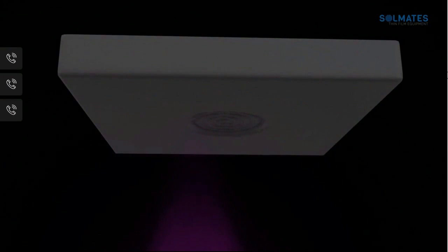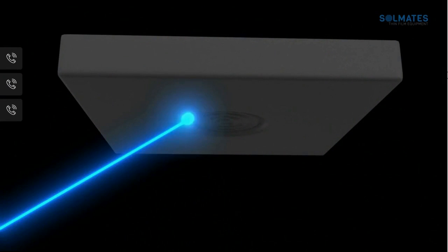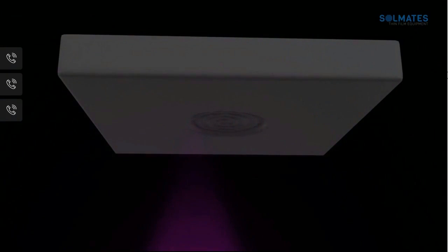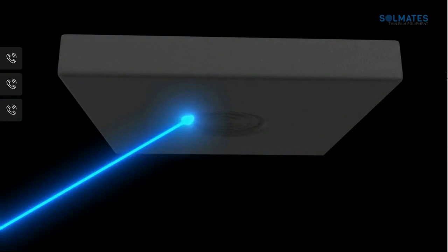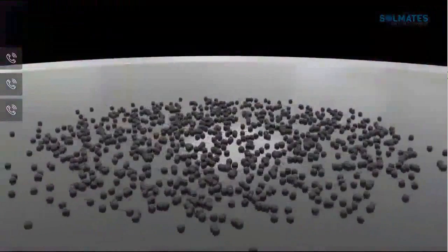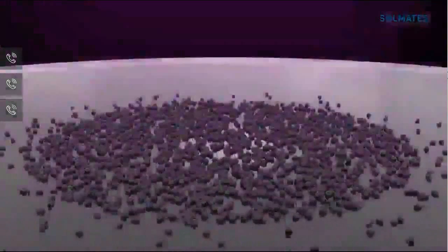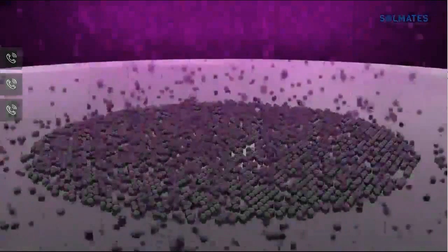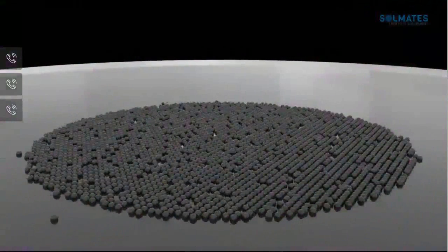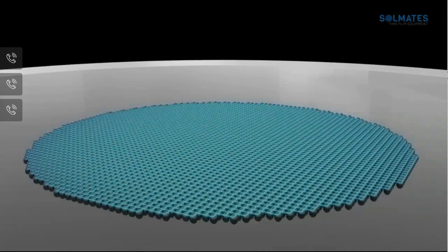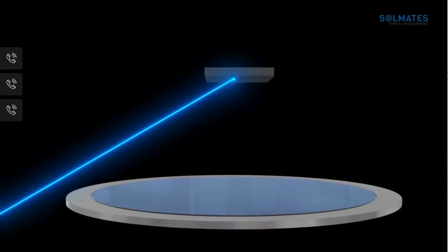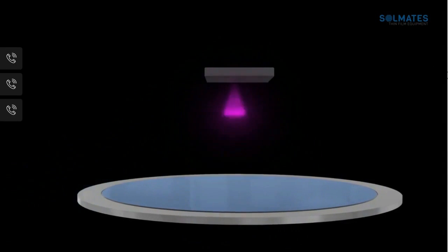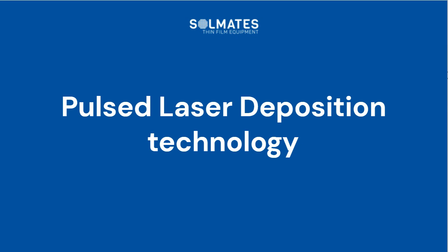There is no argon, not an argon plasma. We don't need to keep a current going. So all the energy of the plasma plume comes from the laser, right? So there is some background gas to control pressure, but the laser is what makes the plasma. It takes only a couple of pulses to make a monolayer. It's a local monolayer on the wafer. We need to fill the entire wafer, of course. But this plasma has excited species, and by scanning the wafer versus the target, you can see that we can build up an entire layer.